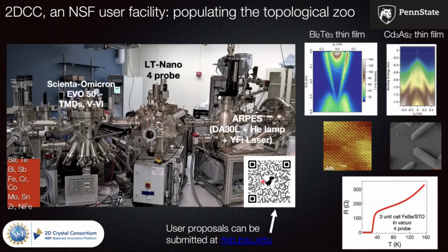And as you can see, for example, with this kind of facility, we've looked at iron selenide with in situ probing of the superconducting transition in iron selenide. That's down here. And then we've looked at ARPES. Now you might wonder, where is cadmium arsenide coming from? There is no cadmium arsenide on this page, and I'll show that on the next page.